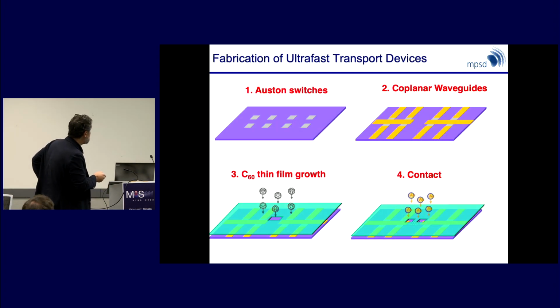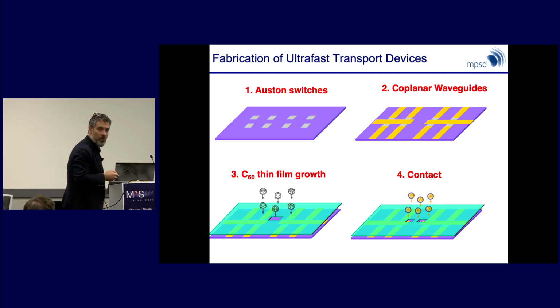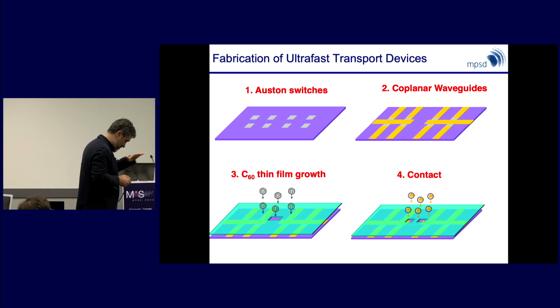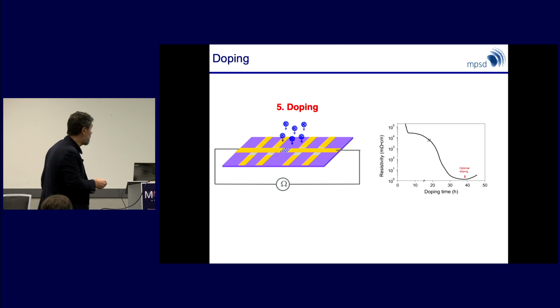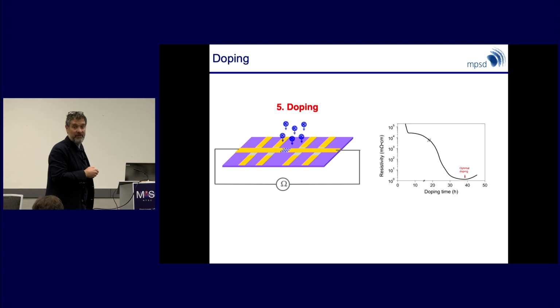These are the fabrication steps that we have taken. You grow these Auston switches, so these are the photoconducting switches. These are standard growth methods. You deposit coplanar waveguides, you put a mask, you grow a thin film of undoped C60, you contact it, and then you read the literature of 20 years ago, and you evaporate potassium on it. You minimize the metallic resistance at room temperature, and this was shown by Zettl's group and by other people: if you do this at the minimum of conductivity of the metallic state, you get a superconductor.